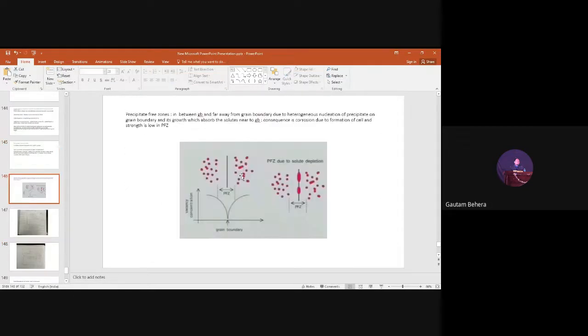And there is a very interesting fact over here. This is a very good image. You can see PFZ, particle free zone. Particle free zone means this zone. You can see this is a grain boundary, right? Here the grain boundary is having precipitates, bigger precipitates. But near the grain boundaries we have no precipitates here. So it is a depleted region. Here precipitate is absent.